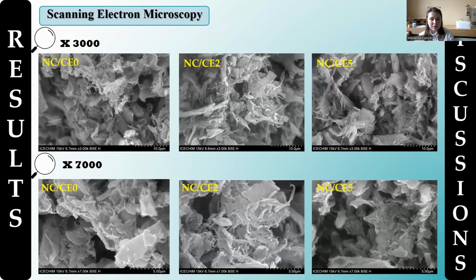As we can observe from the scanning electron microscopy images carried out at the magnifications of 3000 as well as 7000, the structure of nanocellulose is not affected greatly by the presence of the curcumin ethanolic extract, but we can observe a slight compact appearance as compared to the control samples in the left of the slide.